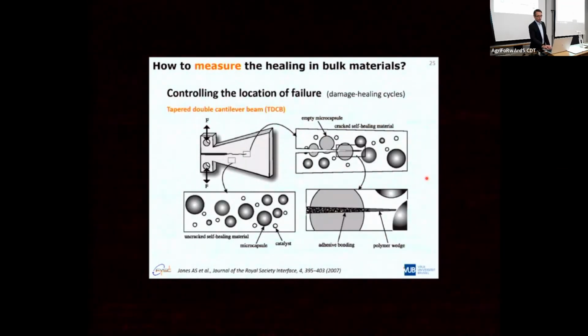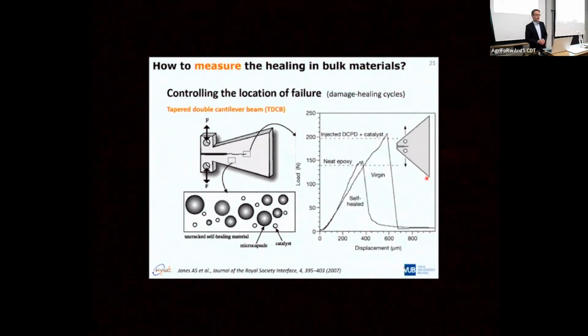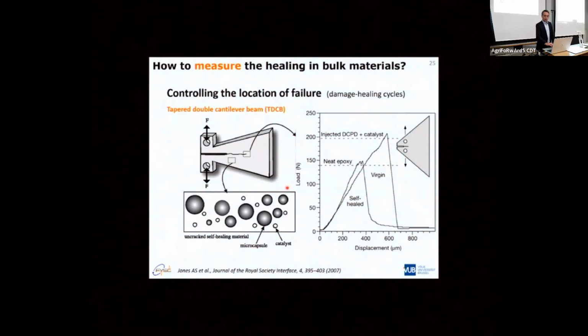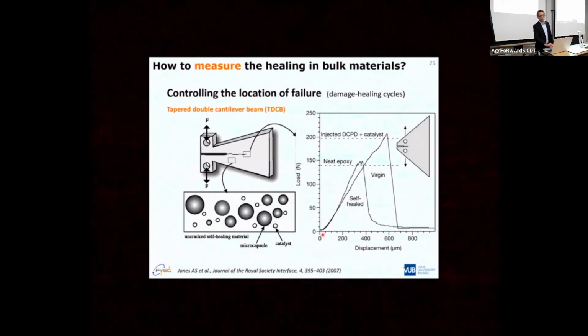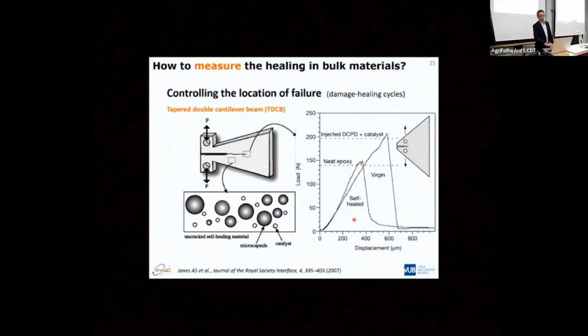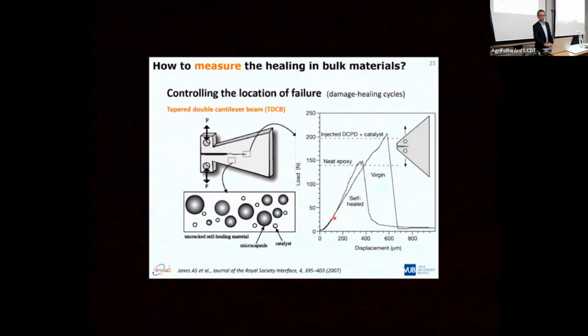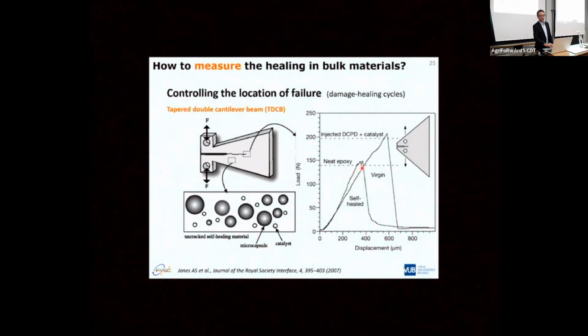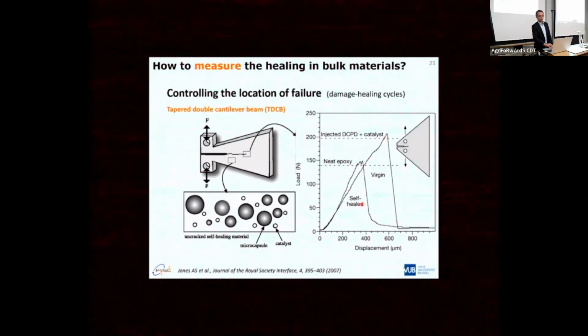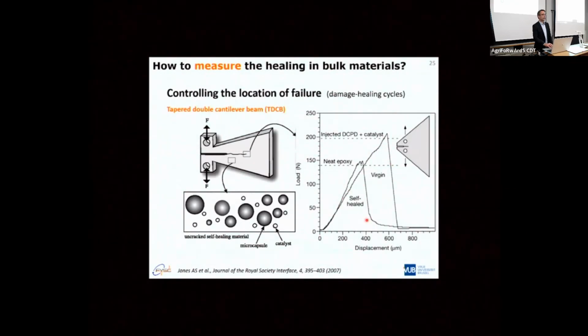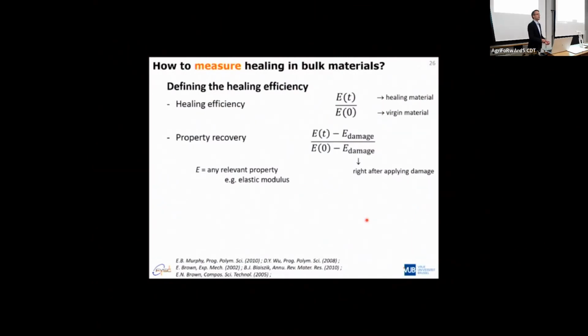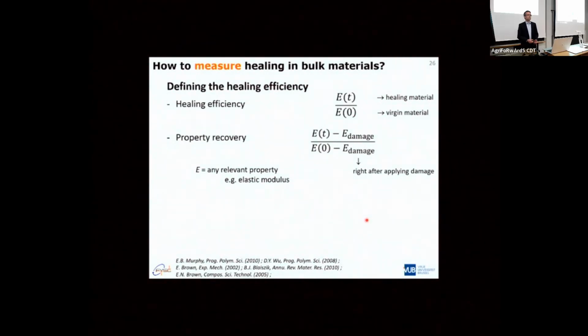In case of the tapered double cantilever beam, you get something like a tensile curve. You load a sample, you do it for a virgin material, you can do it for the self-healed material. You can quantify the, let's say, the mechanical response at small deformations. You can quantify it for, let's say, the maximum levels of load that you can apply, or maximum displacements that you can apply, or of course you can integrate the curve and go to things like toughness. All of these will give you different measures, different healing efficiencies. Even healing efficiency is not something that is generally defined, for which there is only one definition available.